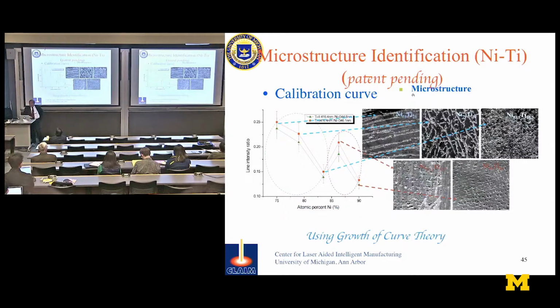Now, how do I do that? What we found is, if you take a ratio of the two primary alloying elements, whatever the alloy, this is a nickel titanium alloy, we tried six different alloys. Whatever the alloy, you take the two primary alloying elements, take the ratio, and plot the line intensity, and basically what you use is called growth curve theory. A lot of things we do, we borrow from the physics community and apply in our engineering. Whenever the microstructure changes, the slope changes.